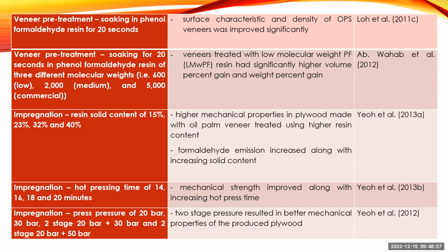Another study looked at veneer pre-treatment, soaking for 20 seconds using different molecular weight resins, and found that veneer treated with low molecular weight PF resin had significantly higher volume percent gain and weight percent gain.